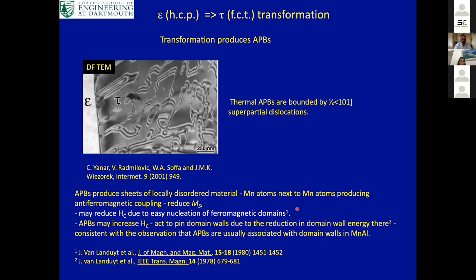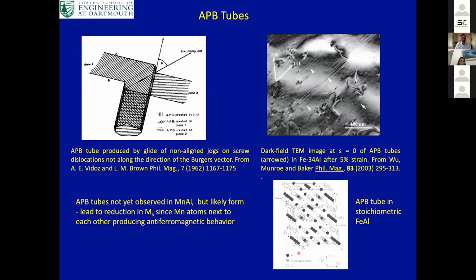One suggestion is that the thermal antiphase boundaries may reduce the coercivity due to easy nucleation of the magnetic domains. An alternative paper suggests they actually pin the domain walls because there's a reduction in domain wall energy there. Interestingly, these two different suggestions were actually made by the same group, but in two different papers. One thing that hasn't been seen in manganese aluminum, but probably exists in the material, is antiphase boundary tubes.